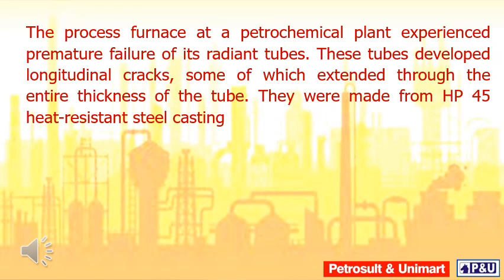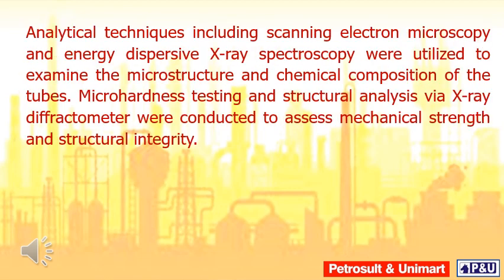The ethane process furnace at a petrochemical plant experienced premature failure of its radiant tubes. These tubes developed longitudinal cracks, some of which extended through the entire thickness of the tube. They were made from HP 45 heat-resistant steel casting.